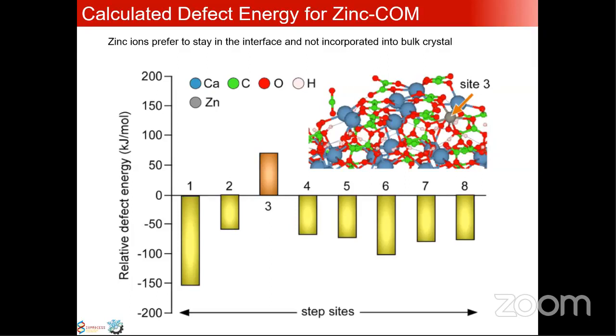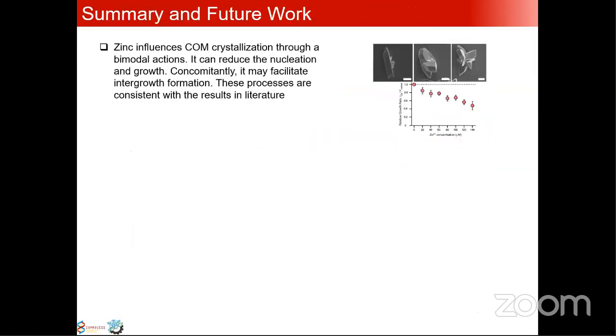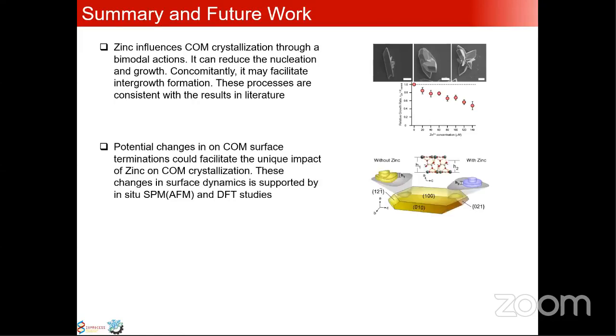an interfacial process. And just to summarize, first, we found out that zinc influences calcium oxalate crystallization through two modes of action: influencing nucleation and growth, as well as facilitating the formation of intergrowth. Secondly, we were able to capture those possible changes on the surface terminations by corroborating AFM and density functional theory studies.